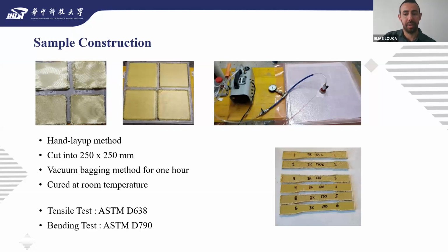Then, the plate of composite material produced by vacuum bagging was machined to produce the samples. Samples for tensile and bending tests were cut to the size according to this standard. 6 samples were prepared for all different cases. All the tests were done at room temperature.